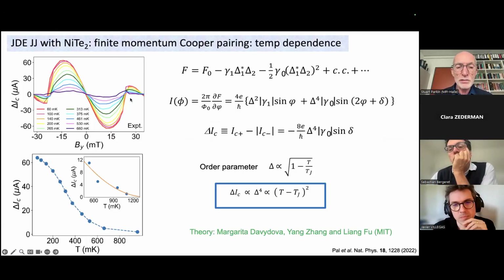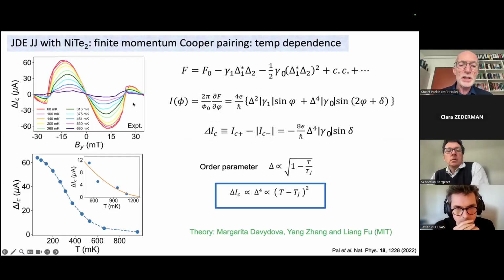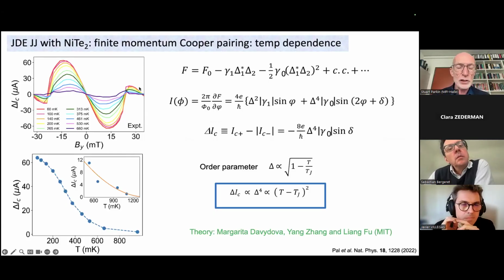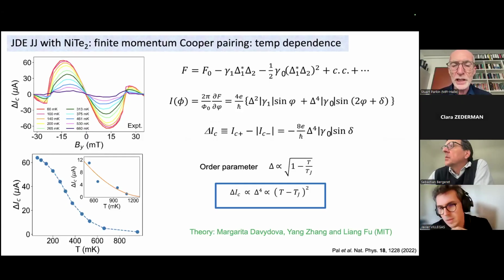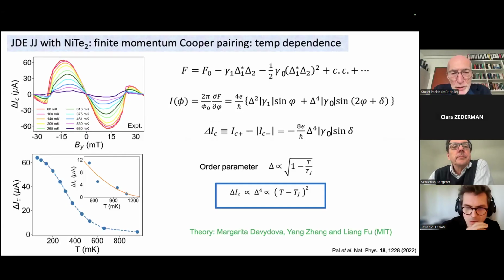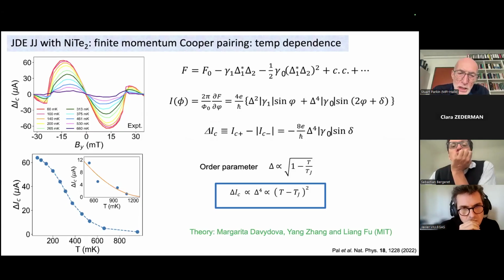But as we further increase the field, the magnitude decreases, and eventually it crosses 0 and reverses inside. As we further increase this magnetic field, we actually see an oscillation in the magnitude of this effect. So what Liang, Yang, and Margarita were able to show was that this was due to this additional phase that the Cooper pairs pick up from the spin splitting of these topological surface states.